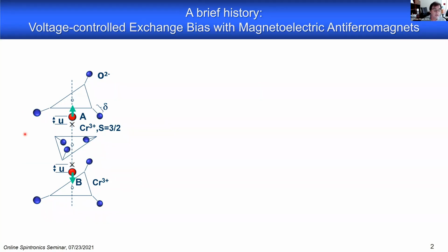So here you see a fraction of the magnetic unit cell of chromia. You see the threefold axis, which we call the C-axis. You see here two chromium 3+ ions and their respective spin ups and spin downs. And you see their oxygen 2- environment, which is nearly octahedral, with some distortion that is exaggerated in this cartoon. But this distortion, in fact, is critical for the magnetoelectric effect. So let's see from the cartoon roughly how we can understand the magnetoelectric effect.